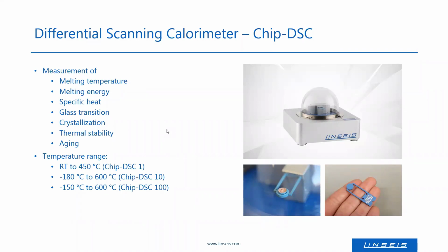So the Chip-DSCs are available in different configurations. One is from room temperature to 450 degrees Celsius. This is good for most applications, but for example, if one wants to investigate the printed material a bit further, or some polymers have a really low glass point, then some further configurations are possible. Here you see a picture of the DSC, and on the bottom you see this small sensor, which is put into the instrument, and in a very small crucible, one places the material one needs to measure. There are also different heating rates possible. So the transition points also depend on these heating parameters. So the faster the cooling, the properties can also change.